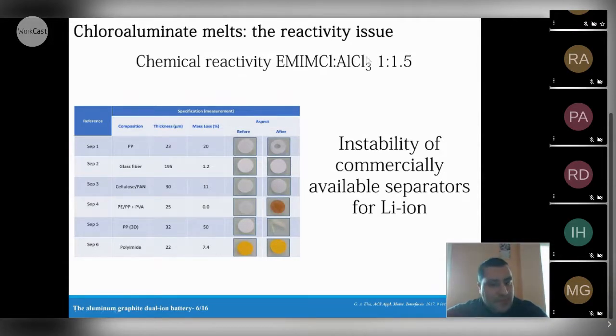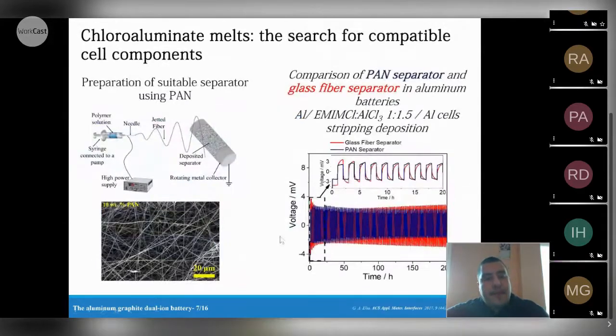And from the preliminary screening, we have seen that none of these separators is suitable for the realization of batteries, because none of them is chemically stable in the chloroaluminate melt. Luckily, we found that polyacrylonitrile is stable in the chloroaluminate melt. And in cooperation with SEI, we use an electrospinning method to produce a non-woven membrane, utilized as separator in this chloroaluminate